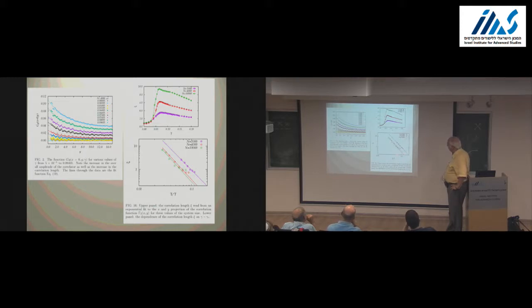And you can show that as a function of the distance from the spinodal point, you have a nice power law with an exponent that at this point we still do not understand, but is an exponent that is very clear. You have sufficient data to show that there is indeed such a divergent correlation length, and there's going to be a lot of work to understand this exponent and compute it from theory, etc., but you know, you have the phenomenon. So basically, this is what you see at temperature zero.